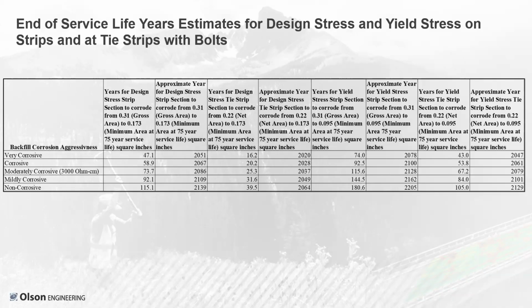stress strip section to corrode from 0.31, the gross area, to 0.173, the minimum area, for a 75-year service life, in square inches. This is coming up with, if it was a zone where the backfill soils were now very corrosive, it would be 47 years. And it would be 59 years for the corrosive to moderately corrosive case, 73.7.